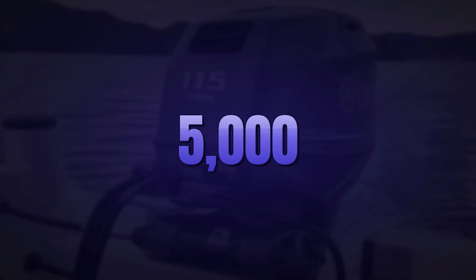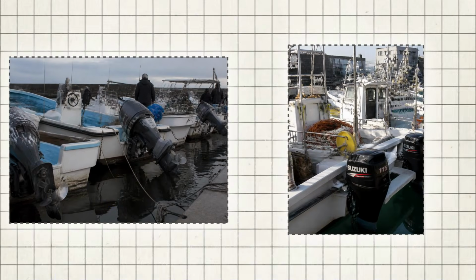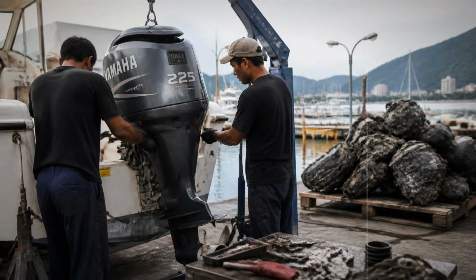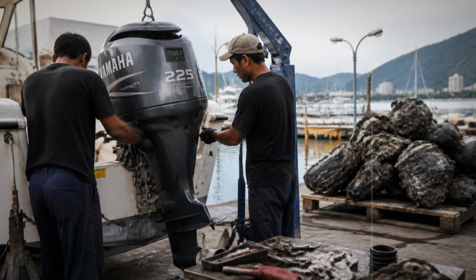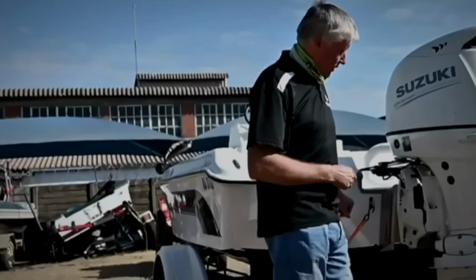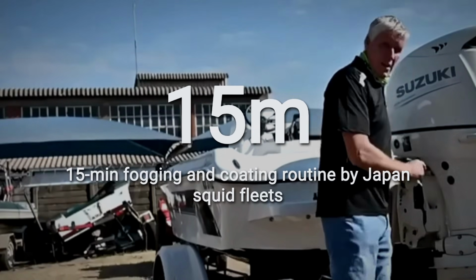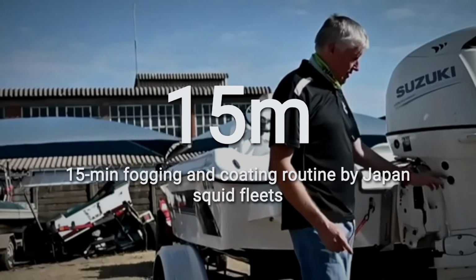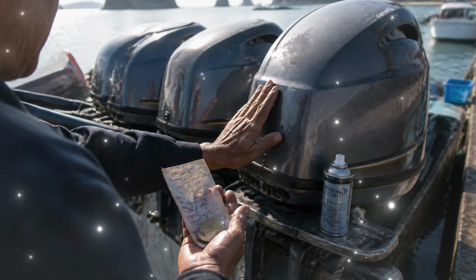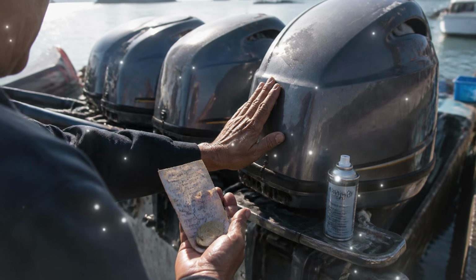original internals. A comparable recreational fleet running the identical engines in the identical water, without that end-of-cycle protection routine, was replacing powerheads at under 2,000 hours. Same engine, same ocean. The entire difference was what happened in the 15 minutes after the last run of each trip, and the couple of dollars of film that bridged the idle months in between.